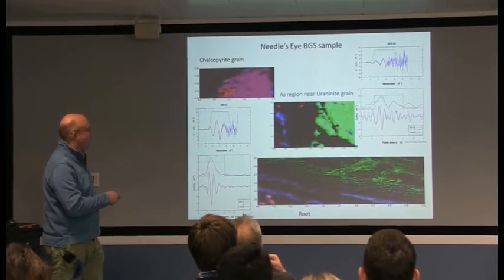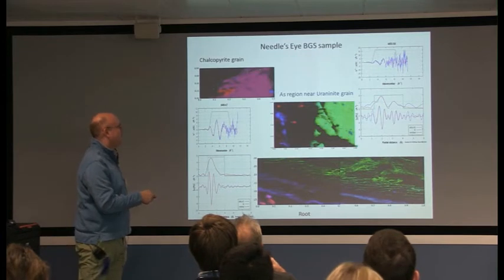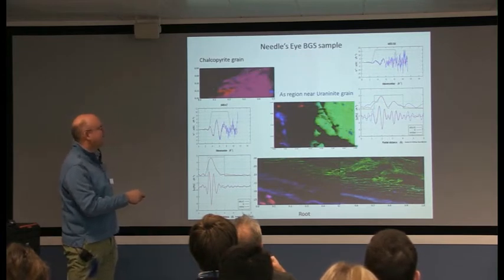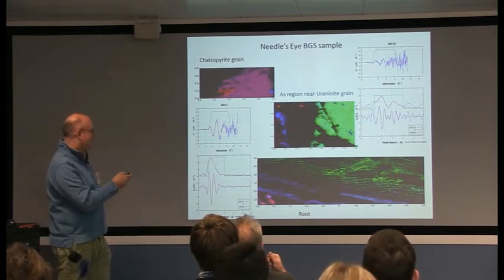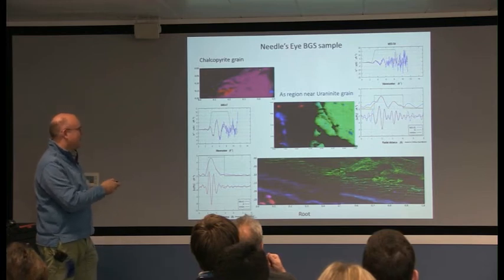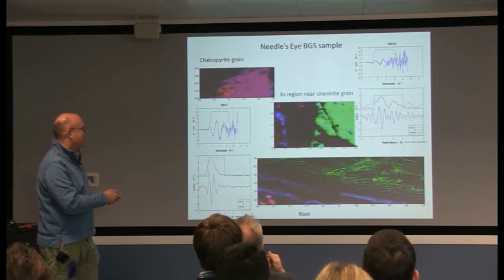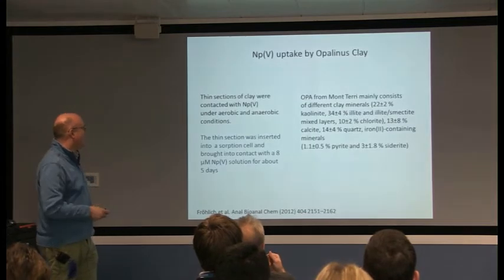On the side of the chalcopyrite, that was slightly higher, hence the data is a bit better quality than the arsenic region near the uraninite grain, which is rather dodgy data. It's pretty difficult to determine much more than that it's also a uranyl group. You can fit some iron in that third shell, but the data is a little bit noisy.